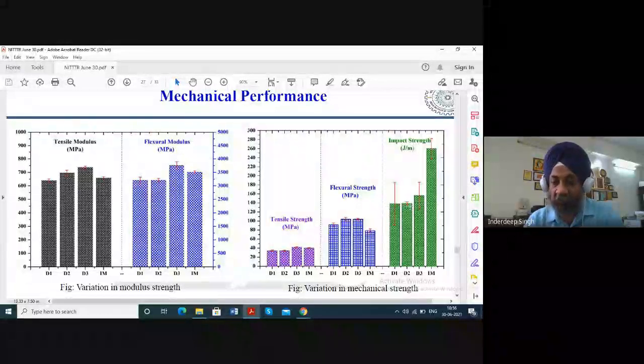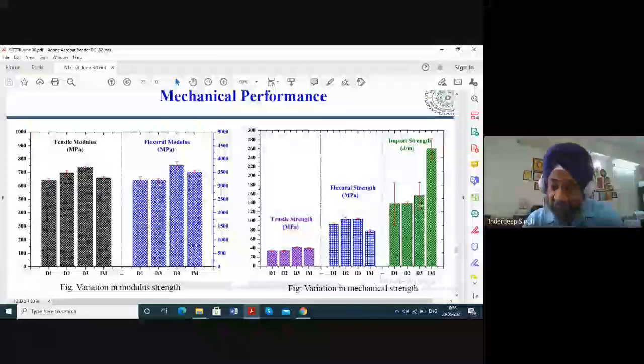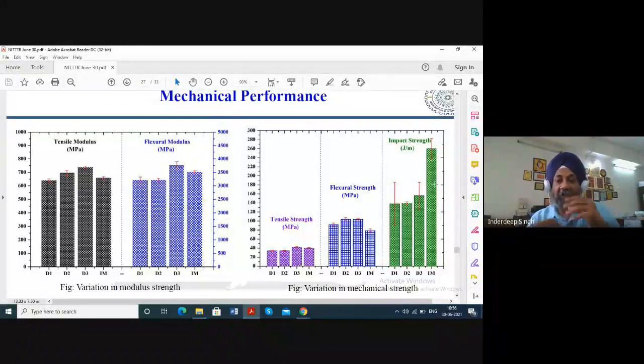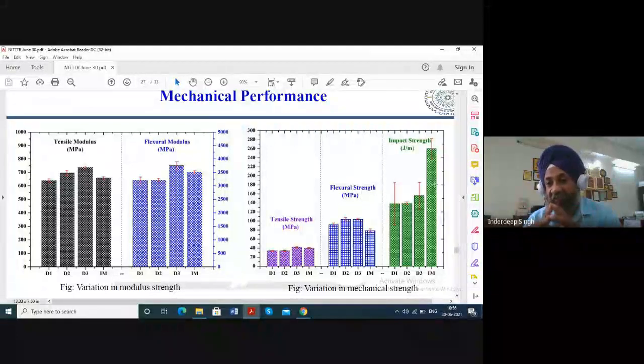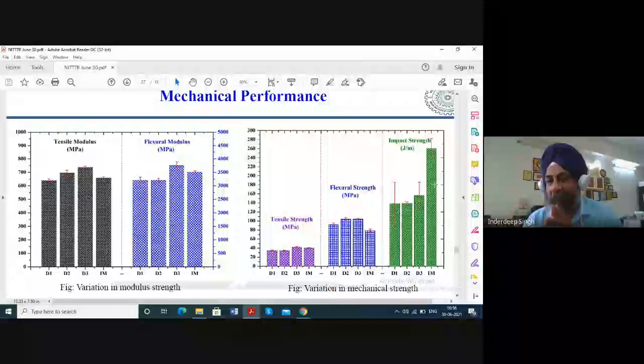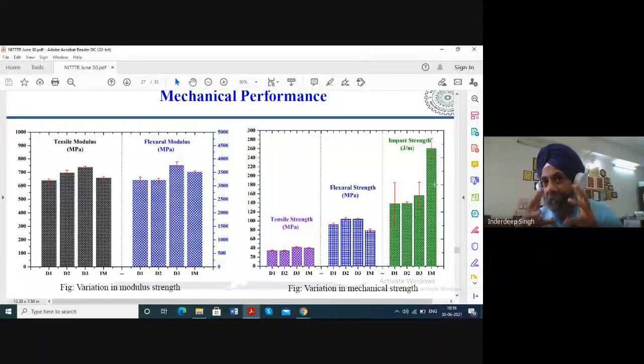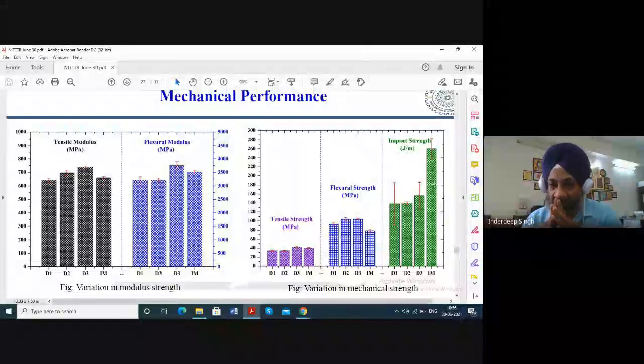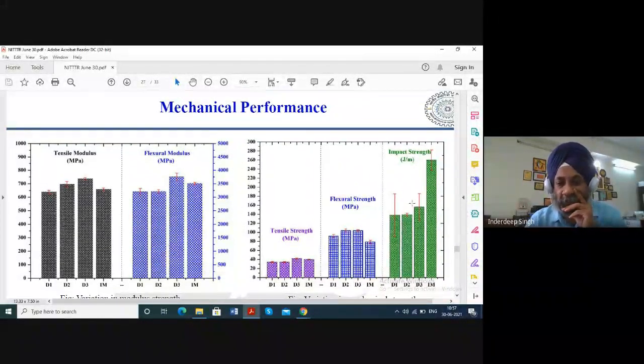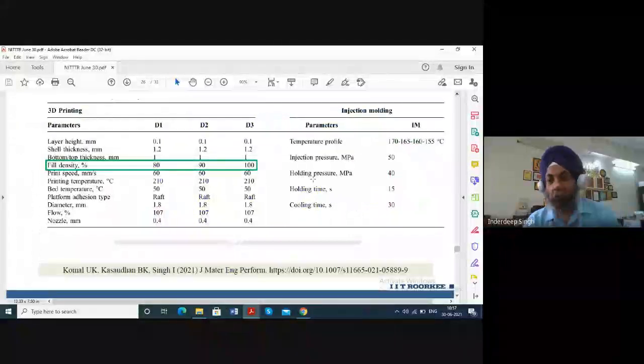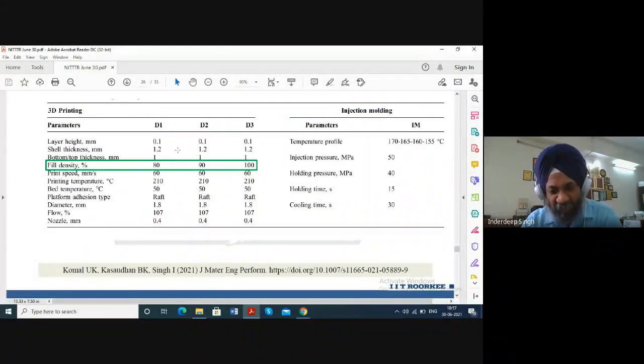Similarly, the impact strength, although in case of the FDM parts, is slightly less as compared to the IM part. So that will depend upon further optimization and further investigation, that how we can improve the impact strength of our FDM parts, or what important parameters govern the impact strength of the FDM parts, because we have optimized these performance parameters, that I again go back, based on the tensile properties only. Some of you may have this question that how these important parameters were optimized. In another study, we only tested the tensile strength of the samples, and we found out these are the best parameters for maximizing the tensile strength of the samples formed by FDM process,